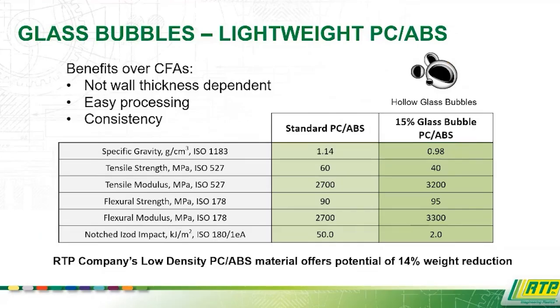If you're looking for the maximum reduction in density where properties aren't so critical, hollow glass bubbles are really your best option for that. And we can see in a standard PC ABS, you take out 14% of the density going from a 1.14 to 0.98. But again, you do lose some of that tensile strength and you get a big drop in your impact resistance. But hollow glass bubbles do have an advantage over something like a chemical foaming agent, a CFA, which are wall thickness dependent. They don't process well. It's hard to make work right.